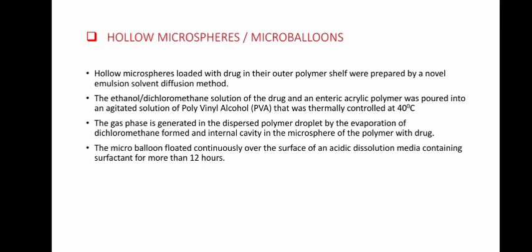Hollow microspheres or microballoons. Hollow microspheres loaded with drug in their outer polymer shell were prepared by a novel emulsion solvent diffusion method. The ethanol dichloromethane solution of the drug and an enteric acrylic polymer was poured into an agitated solution of polyvinyl alcohol that was thermally controlled at 40 degrees Celsius.